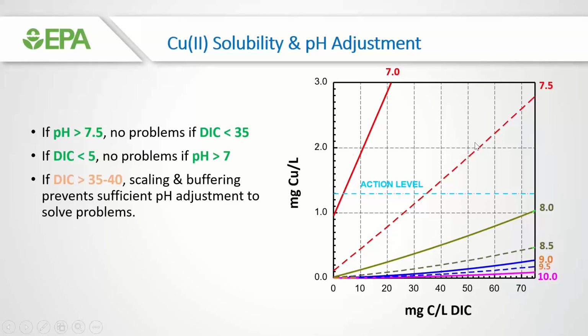So what do you do about that? Well, can you raise the pH? That could be an issue because it might take a lot of base to raise the pH in a water that has a high DIC or high buffer intensity. Second of all, a lot of the waters that we deal with, at least in the Midwest, also have a lot of calcium. So you're also talking about some scaling issues that might come about by trying to increase the pH. So what do you do about this difficult, challenging high DIC water that affects copper levels?